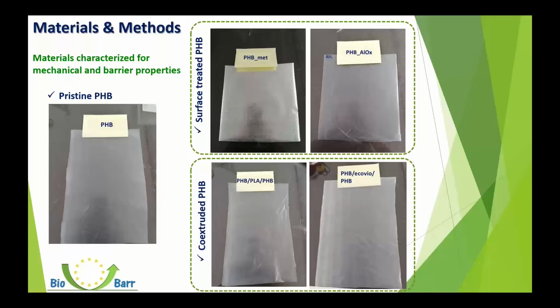We focused our attention on the characterization of a commercial PHB grade provided by BioBarr. So we characterized this polymer for mechanical and barrier properties, and then we characterized two systems developed during the project: the surface-treated PHB films, in particular metallized PHB and AlOx-treated PHB, and then we characterized the co-extruded PHB films. The co-extrusion was performed with two compostable polymers in order to not affect the compostability of PHB. The co-extrusion was performed with PLA and Ecovio, a compostable polymer provided by BASF.